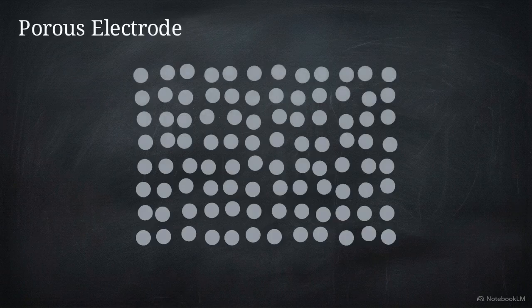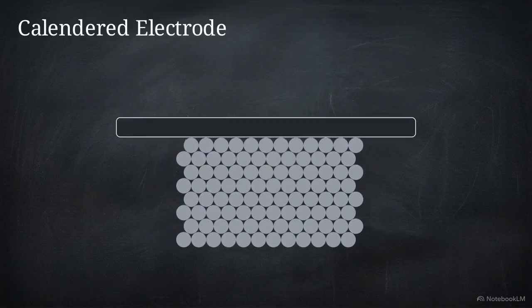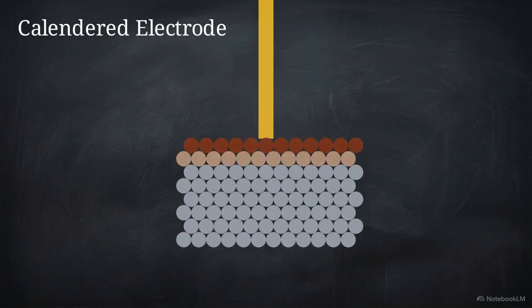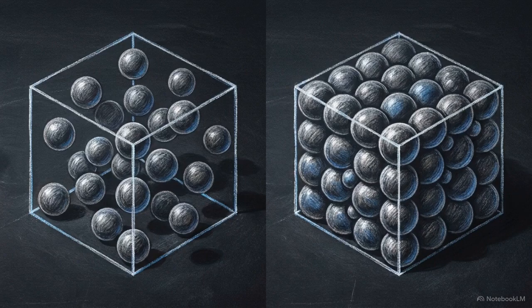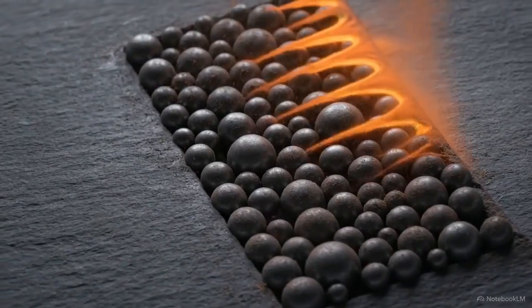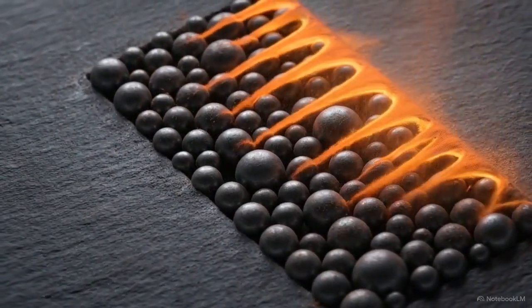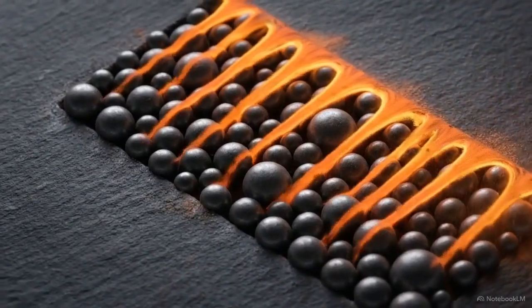To understand why compression restricts the damage, we have to look at the microscopic lattice structure of the active material. In a standard porous electrode, air gaps act as thermal insulators. Laser heat pools at the surface, destroying the top layer. Calendering forces particles together, increasing thermal conductivity. Instead of pooling, the tightly packed matrix rapidly channels the heat downward. Lower porosity means more material is packed into the exact same volume. It takes a much higher amount of total energy to vaporize that mass. The compressed lattice essentially operates as a highly efficient heat sink. It diffuses the thermal load rapidly, suppressing the localized surface vaporization.